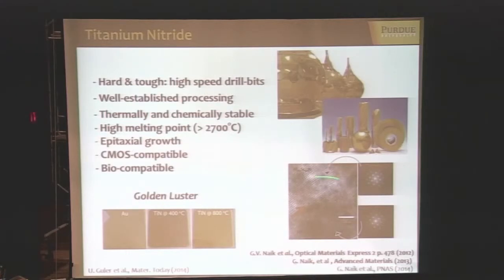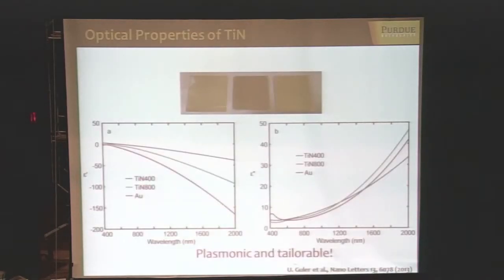Here you can see that indeed you could grow it epitaxially—this is the titanium nitride we grow, and it has single crystal quality. This is a so-called non-stoichiometric material, meaning you could actually design its properties. If you start at the stoichiometric point, with 50-50% titanium and nitrogen, and slightly move from that point by introducing defects or vacancies, you dramatically change the charge carrier concentration, and as a result the real part of the electric permittivity also changes dramatically.